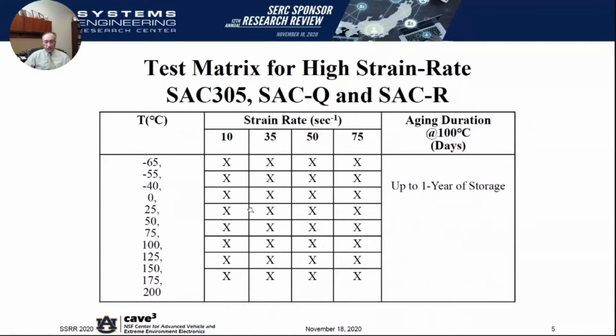These are some of the test conditions that we are studying. As I mentioned, there are a couple of different temperatures that occur in this test. So the first set of temperatures are operating temperatures. They range from -65 to +200. We are also looking at a second temperature, which is the storage temperature for sustained thermal storage, and that is 100 degrees centigrade. For the most part, we also are taking data on 50 degrees centigrade.